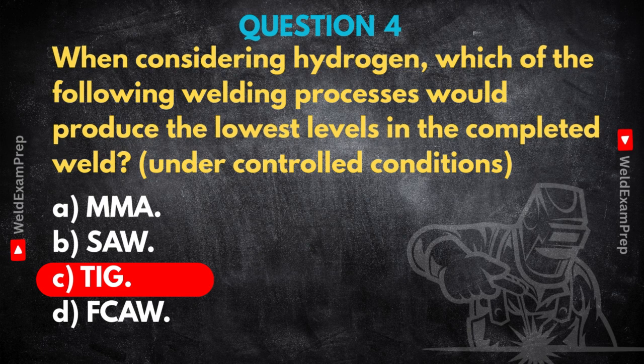That's scary. It is, especially in high-strength steels or thick sections under restraint. It can lead to catastrophic failures that weren't apparent right after welding. So for critical applications, choosing a low hydrogen process like TIG and ensuring all controls are in place is absolutely paramount. Really drives home the importance of process selection and meticulous control.